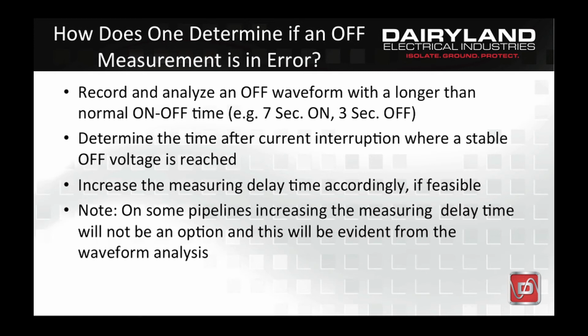This waveform will readily show whether the off voltage is stabilized at the time delay normally used to take an off potential measurement. If it has not stabilized by that time, determine whether one can increase the measuring delay time and take an off measurement after the off voltage has stabilized due to the transient current being dissipated. If feasible, then increase the measuring delay time accordingly to obtain an accurate measurement, as this is the simplest solution.